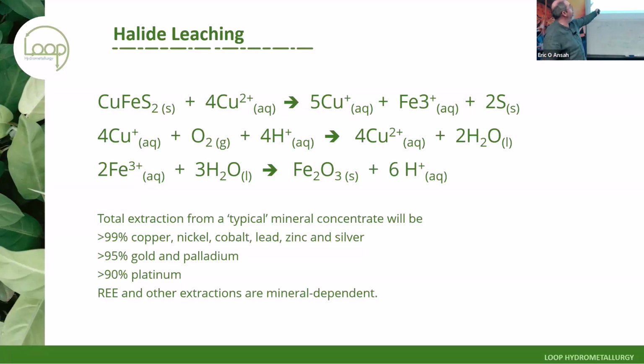So our basic leach reaction is copper sulfide reacting with cupric to make cuprous ions and ferric ions and elemental sulfur. Now, the formation of elemental sulfur is important because that means that for every molecule of mineral that you're leaching, you're only needing to oxidize 2 electrons of sulfur rather than 8 electrons of sulfur, and therefore your oxidant addition is a great deal less. In turn, that means that when we reoxidize the cuprous ions with oxygen, we're doing it with air, not with pure oxygen. In a side-by-side comparison to the Albion process, as an example, we did an apples for apples comparison on a published site. Our whole plant costs less than their oxygen plant.